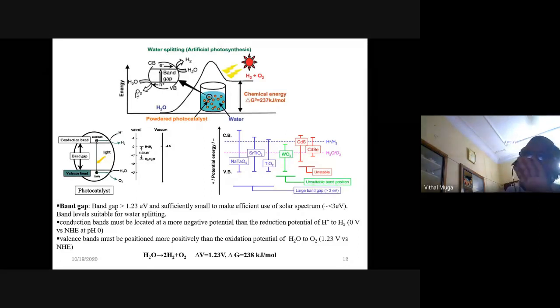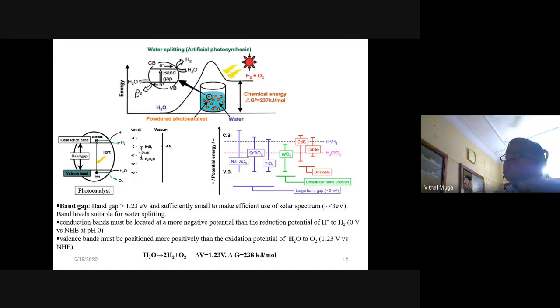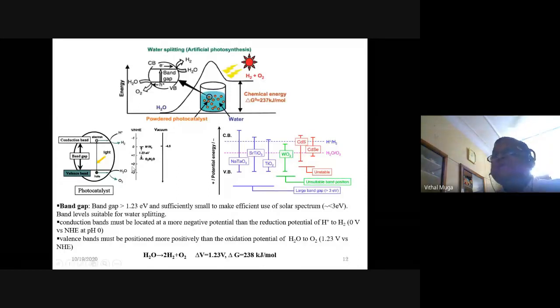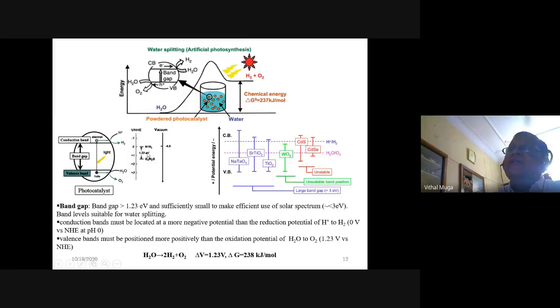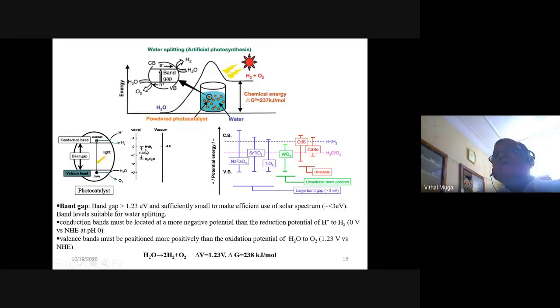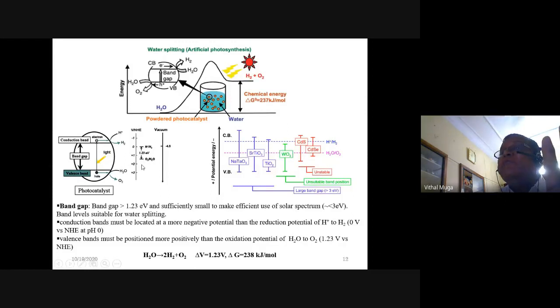So is it sufficient if the band gap energy is, let us say, 1.23 volts? Then also it is not sufficient, because the oxidation and reduction potentials also should match. Normally I have not shown the diagram here. This is 0 and this is 1.23. See, I have given it here. 0 is the hydrogen redox potential. 1.23 is the oxygen redox potential. Now, the conduction band minimum should lie above 0 and the valence band maximum should be below 1.23.